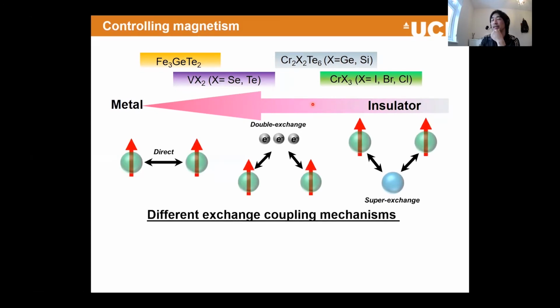And in terms of the basics of magnetism, if you have really localized magnetic ions as an insulator, the exchange coupling tends to go through other elements. This is what we call super exchange coupling, and the spin is purely isolated, so the Heisenberg picture would normally be very suitable. And then when you start doping, you start populating charge carriers, and some of the exchange coupling can be mediated through these charge carriers. So these two magnetic ions are communicating through the spin of the charge carrier. This is what we call double exchange coupling or RKKY interactions.